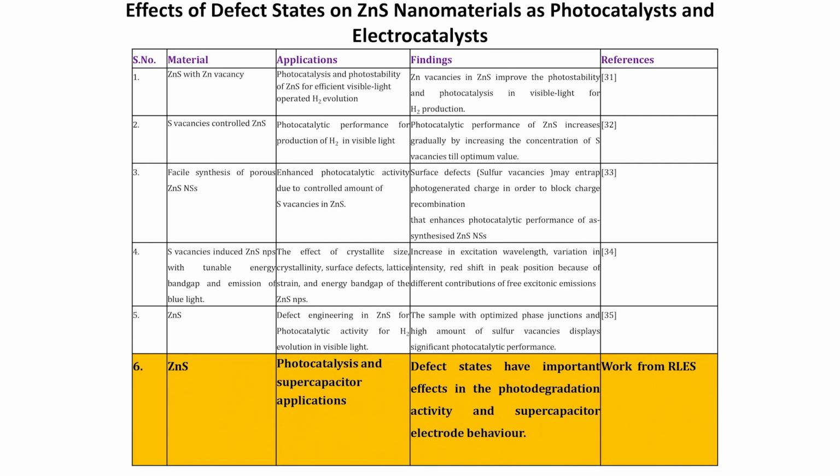ZnS sphere grown on carbon textile, flexible full solid state supercapacitor, and the ZnS carbon tubes electrode exhibits a high capacitance value of 747 farad per gram at 5 millivolt per second in aqueous LiCl electrolyte. And the graphene doped ZnS nanoparticle which has been developed in our lab is for the electrocatalytic study.